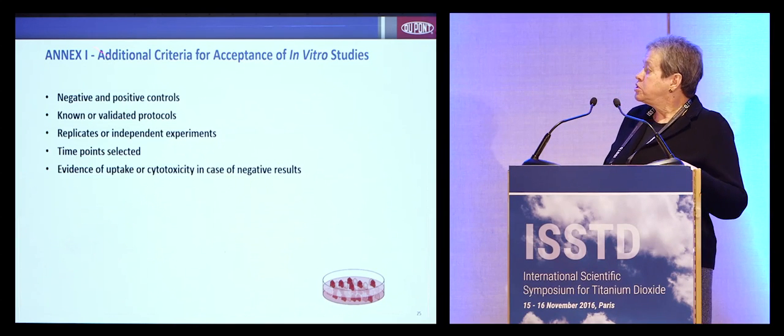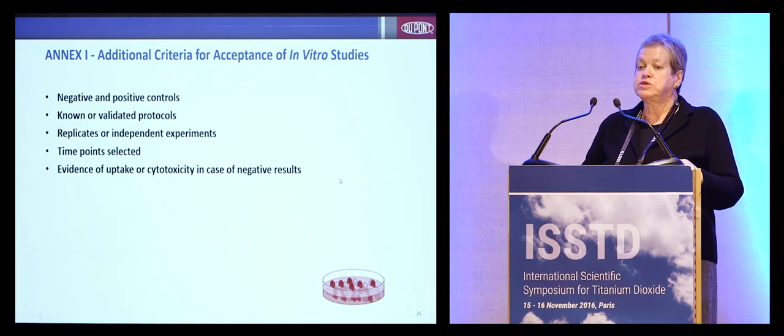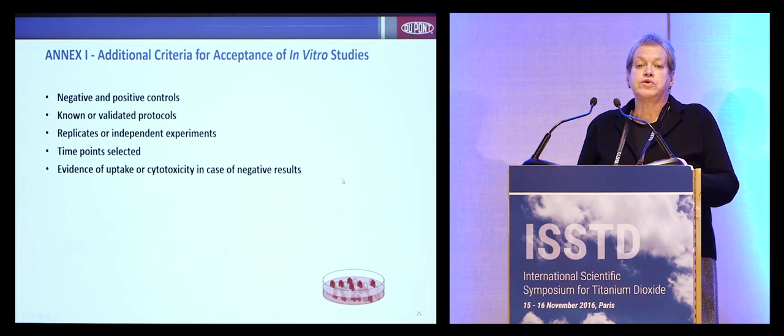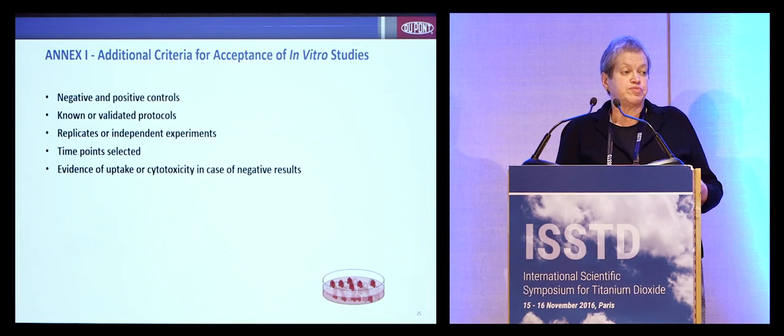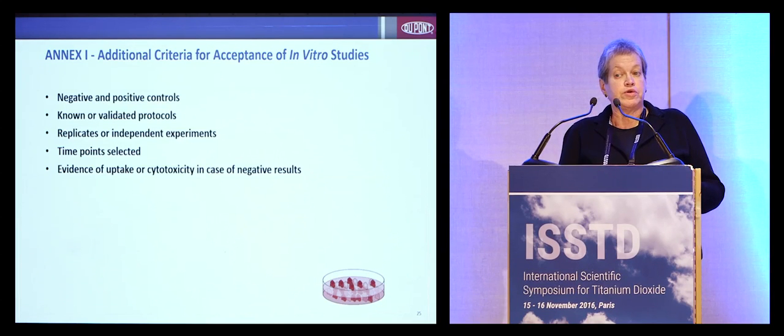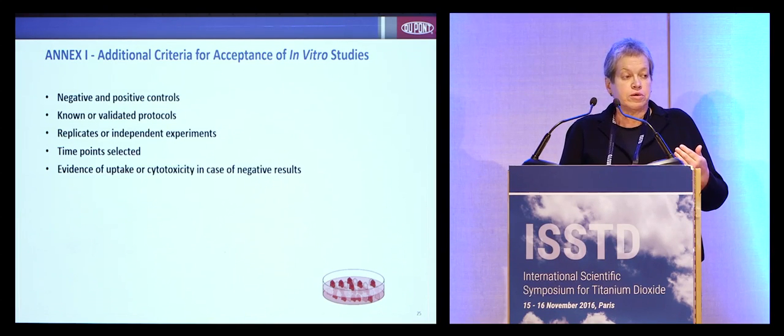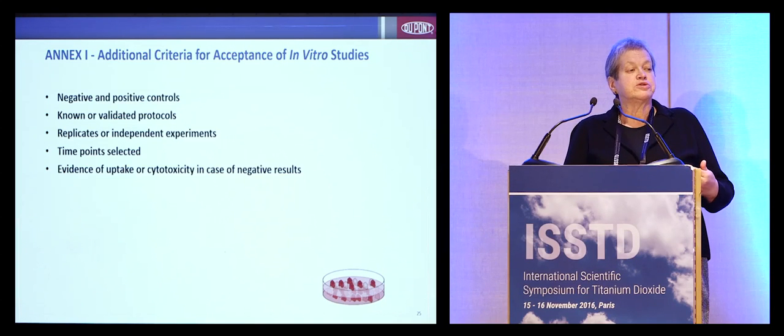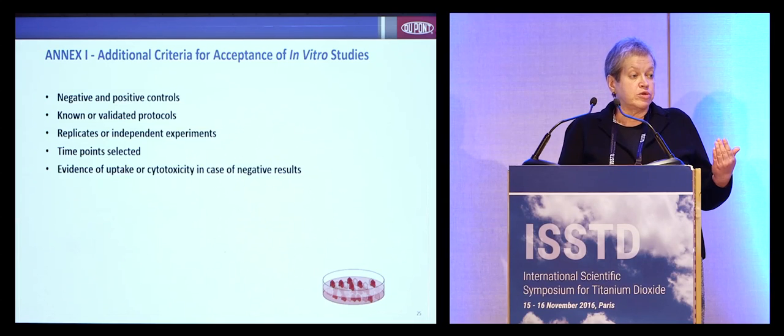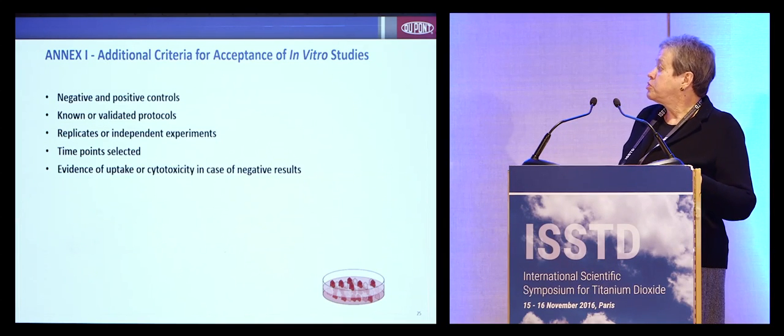Another little stop for consideration could be here, evidence of uptake or cytotoxicity in case of negative results. This is not really a criteria that we normally have to apply to in vitro testing. We test up to a guideline dose level. We see cytotoxicity if we see it, but we are not mandated to demonstrate that there actually is any exposure of the cell. It's not unusual that you test up to a guideline limit dose that for many in vitro systems today is 2,000 micrograms per mL, excuse me. You see nothing, but this was the limit dose, and you are supposed to be clear to go.